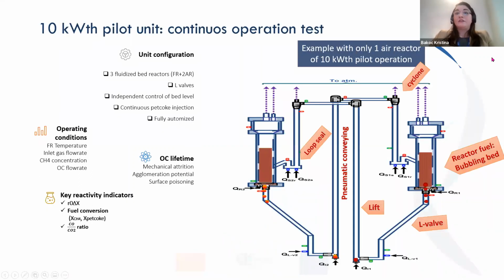So this is the presentation of the 10 kilowatt pilot unit that has been used for continuous operation tests. Here in this little scheme, you see the fuel reactor and only one of the air reactors. However, in reality, we have 2 air reactors to achieve the complete oxidation of the material. Furthermore, there is a carbon stripper above the fuel reactor that serves for separating the unreacted petcoke in the case of petcoke injection, and the entire system is fully automated. The most significant operating conditions that were followed throughout this test are, of course, the temperature of the fuel reactor, the flow rate of the inlet gases that could be adjusted, the methane concentration to adjust the level of reduction in the case of gas fuel tests, and of course, the flow rate of oxygen carrier itself, which has to be ensured to be continuous.